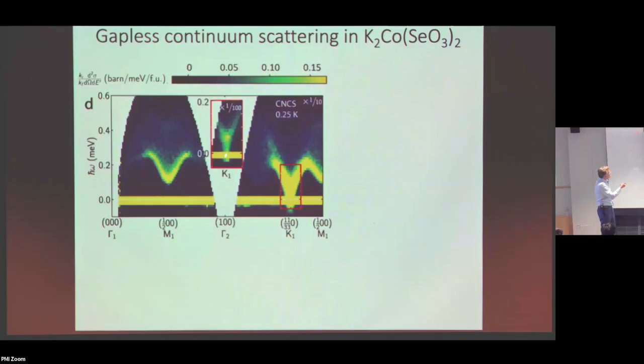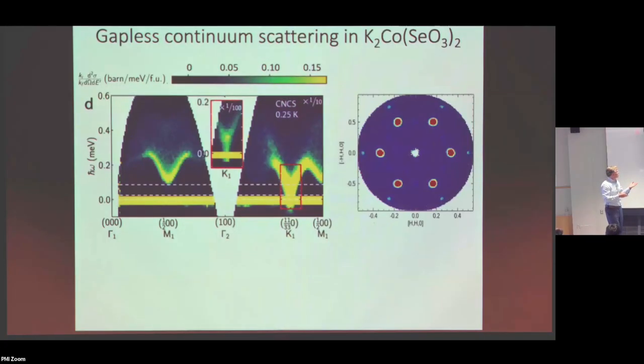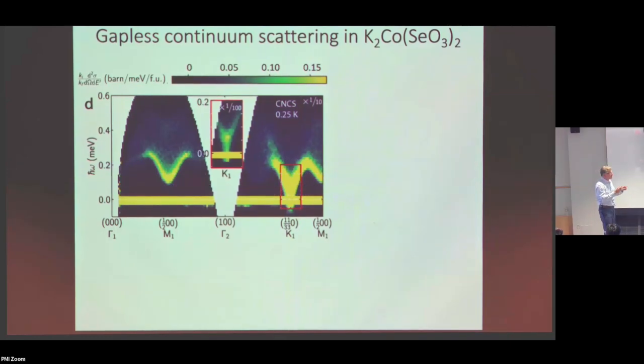But the presence of this gapless part of the spectrum, that is our indication of a broken continuous degree of freedom. So the Goldstone theorem: when you break a continuous degree of freedom, then there has to be a gapless mode. And so you ask yourself, where could that gapless mode come from? I'm going to mention that a little later, but eventually we will relate it to this in-plane transverse component, because that's what can break the rotation symmetry.